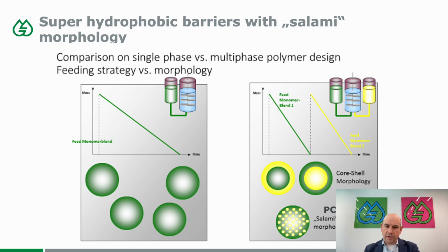The individual domain size here is approximately 10 times smaller than in a conventional polymer. So as a result, when you apply the same film thickness of this polymer compared to a standard polymer, you're getting 10 folds more layers of these hard segments, which then ultimately leads to, let's say, a much more perfect film formation and a much longer diffusion way for water and water vapor. So that gives us these extremely good MVTR properties that we are going to look more into detail in the coming slides.